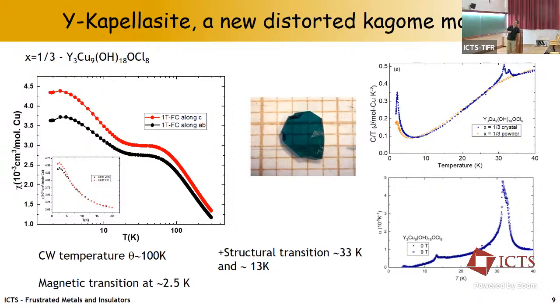It shows Curie-Weiss behavior at high temperature with fairly large, 100 Kelvin, antiferromagnetic interactions. And at low temperature, there's a separation of field-cooled and zero field-cooled with a maximum around 2.5 Kelvin, likely from some magnetic transition at this temperature. And actually, in the heat capacity, you should look at the blue points there. There is a strong, very nicely resolved peak at this same temperature. But in the heat capacity, there is also an additional feature. Here you see there is a double structure around 33 Kelvin, which you don't find here. So it's certainly structural in origin.